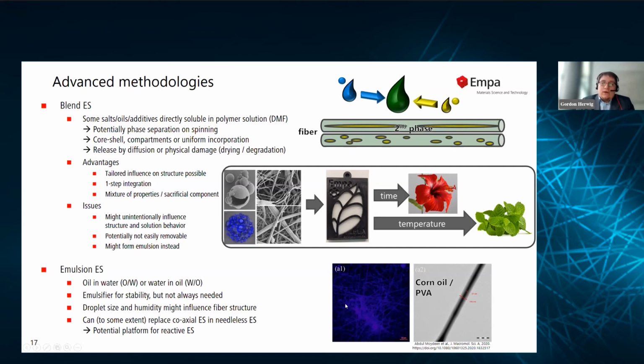And of course, you can use it for reactive electrospinning. What we've used this blend for, we can also use particles or emulsions directly that we can solidify before or after. And we've incorporated, for example, in a completely PLA composite, everything based on PLA, nice fragrance release over time. So still after a year after manufacturing, there's still a nice odor of hibiscus. And we have a certain thermoresponsiveness so that when we heat it up, it suddenly smells like mint, which is very nice for some, let's say, textile applications, but more importantly, also for biomedical applications, because this can easily be replaced by certain drugs.